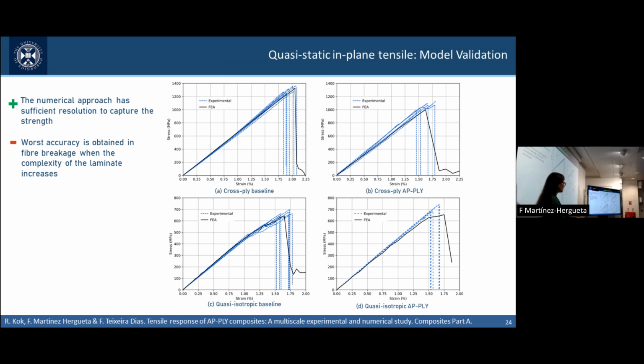We can see that in any case, we are always capturing the stiffness. In the case of the cross-ply laminates, we can also capture decently the maximum strength and the reduction in strength due to the undulation. In the quasi-isotropic laminate with the baseline, we can also capture the softening due to the matrix cracking. It's a little bit more complicated to capture the strength of the AP-PLY laminate. That's because our models have a reduced number of finite elements within the undulation regions, and since the complexity of the architecture increases, the accuracy of the multi-scale model also decreases. But let's say that we are still in a decent range.